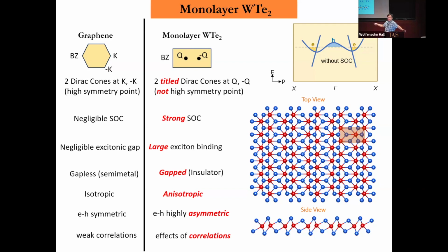Okay, this is not a high symmetry point, and it's in the middle of the Brillouin zone. That's one key difference. The Dirac cone is not really a perfect linear line - instead, here we have a tilted cone, something like this. So the cone is tilted and very highly asymmetric between electrons and holes, not like graphene which is very symmetric.